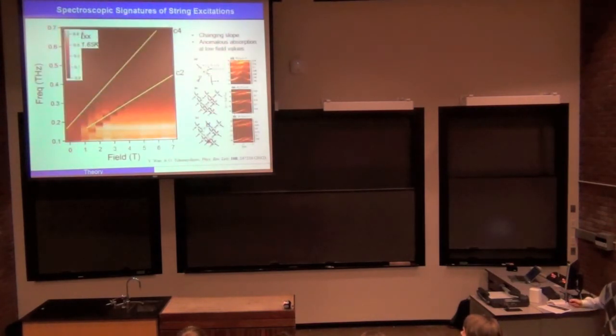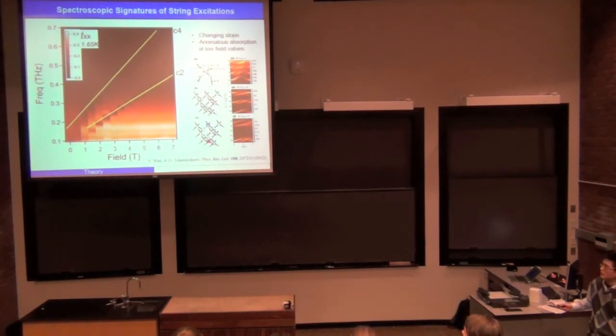Especially if you look at the mode C4, it widens significantly as the field decreases. And also we see this interesting anomalous magnetic absorption in the low field region. We believe all those signatures, the changing slope, the widening of this peak, and the existence of magnetic absorption at low field, are all signatures of the existence of quantum strings in the material, especially in the low field regions. Because if you look at the theory, when the field is low, you are expected to have overlapping bands of strings with different lengths. As a result, we would expect to see this quite broad magnetic absorption, which goes away as you apply a strong magnetic field.